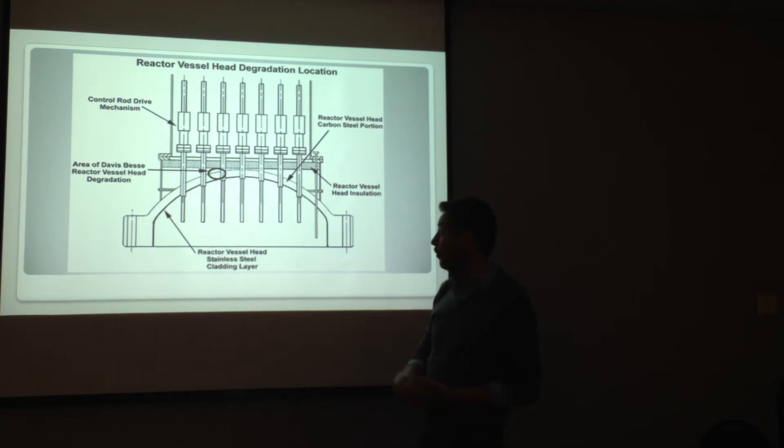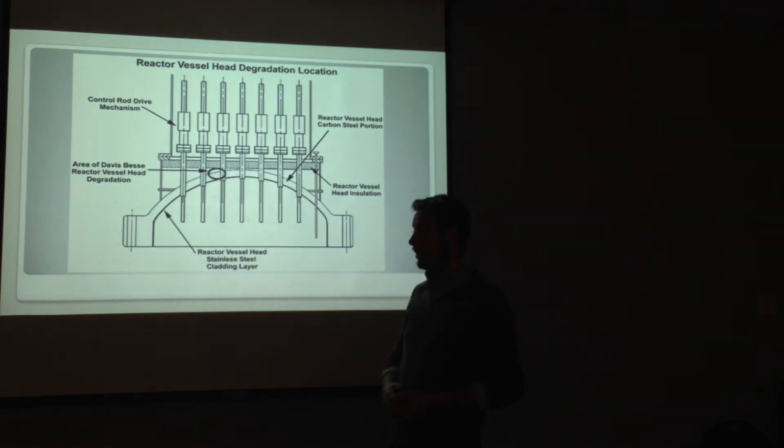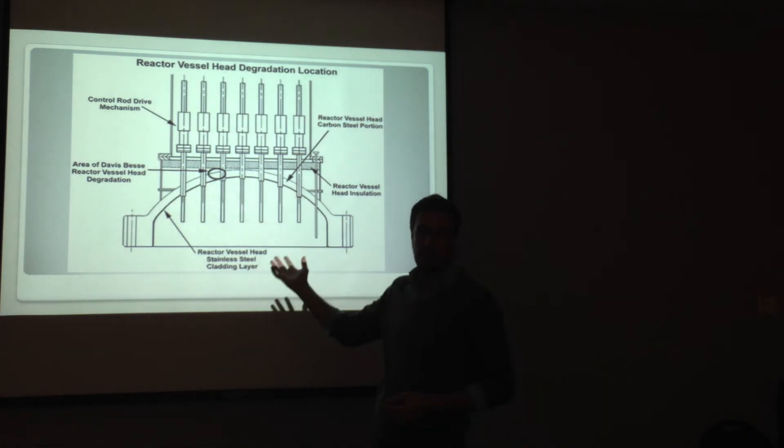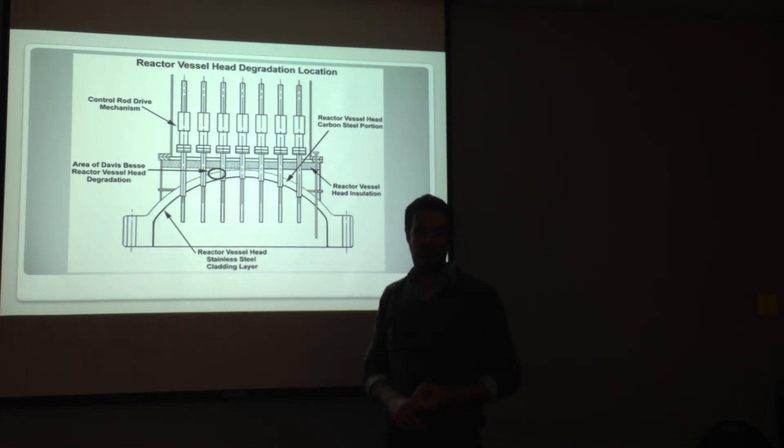Also, there was a misconception that when the primary water leaves and flashes to steam, that the boric acid that's left is so dry and concentrated that corrosion is inhibited. That turns out not to be the case. So, several things were discovered from this and it was good that the incident didn't occur. But, obviously, the understanding of how boric acid can be introduced into the atmosphere and introduced to systems that aren't prepared to deal with it was a big issue.